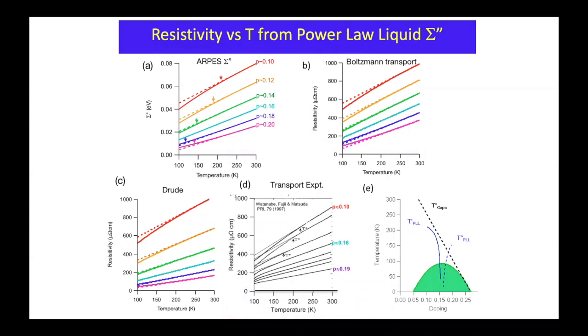I can plot versus temperature. And here's sigma double prime at omega equals 0. And here's the family I get from overdoped to near optimal, because optimal is fully linear, and then underdoped. And with these, and since we also measure velocities around the Fermi surface, we can calculate the resistivity using a certain number of approximations, either a Boltzmann type model or a Kubo type model, and see the calculated resistivity from the ARPES, and this is the measured resistivity.